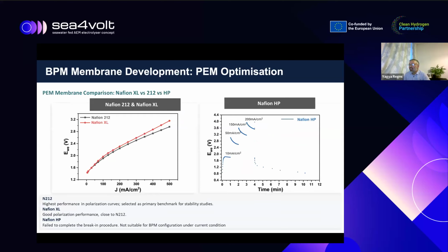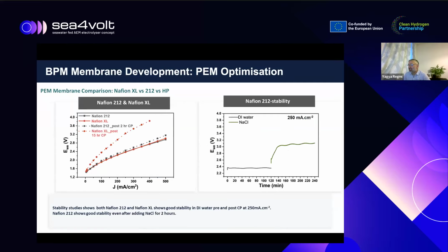Next slide, please. In terms of PEM optimizations, we used the standard Nafion 212, although it is thick, and we also use Nafion XL, which is similar to 212, except that it has mechanical fibers inserted into the membrane for mechanical stability. Similarly, we also looked at other options, something like Nafion HP, and you can see Nafion 212 and XL perform very similar, and you can get to 500 milliamp per cm square below 3 volt cell potential. HP, on the other hand, doesn't work as well for us. This is just a flavor to give you what we are doing in order to select different components. Next slide, please.